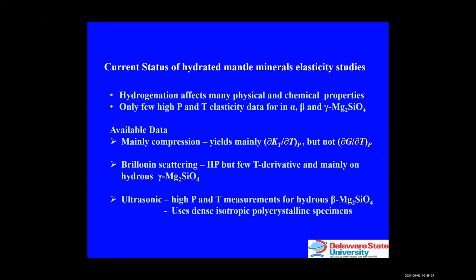Much of the temperature derivative data, or the main source, comes from compression studies, which yield only information about the isothermal bulk modulus, but not the shear modulus. There are, of course, some Brillouin scattering measurements of the bulk modulus and the pressure derivative of the elasticity of hydrous wadsleyite and hydrous ringwoodite, and also a few temperature derivative studies, but still mainly on the hydrous ringwoodite. So using the ultrasonic techniques and the ability to make suitable polycrystalline samples, we are in the process of conducting elasticity measurements at simultaneous high pressure and temperature for the hydrated wadsleyite phase, and hope that if we can do it well, we then move on to study the hydrous ringwoodite.